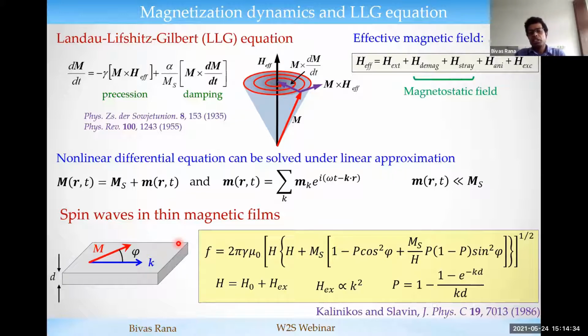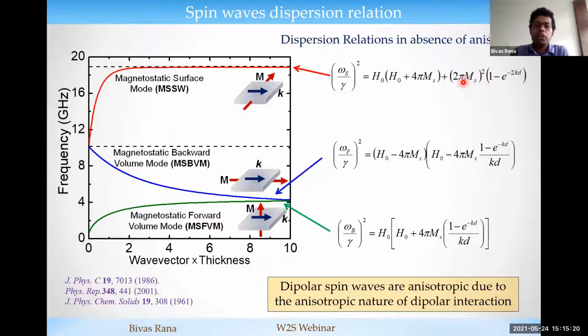For magnetic thin films it is quite complex. The spin wave frequency depends upon many factors. Here the H is composed of the external magnetic field and the exchange field, where the exchange field is proportional to the square of the wave vector of the spin wave, and the P can be related to the wave vector and the thickness of the waveguide in this manner. So this is the dispersion relation of the spin wave. Depending upon the direction of the magnetization with respect to the wave vector, the dispersion relation can be different due to the anisotropic nature of the dipolar interaction in the system.